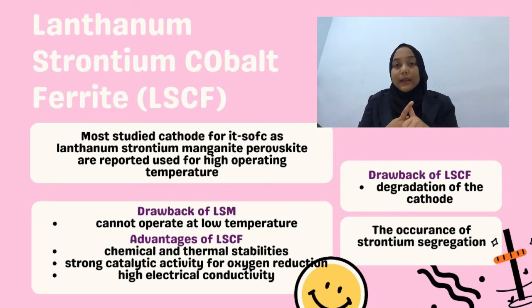After comparing LSM, LSCF, and BSCF, LSCF showed that it is the most studied cathode material. The chemical stability of LSCF is the main reason why it is used in intermediate temperature SOFC. Even though LSCF comes with a lot of advantages such as good electrochemical performance at low temperature, the existence of cobalt in the MIEC material increases the thermal expansion coefficient of the cathode, which leads to incompatibility with the electrolyte. Due to that, various cobalt-free materials have been developed.